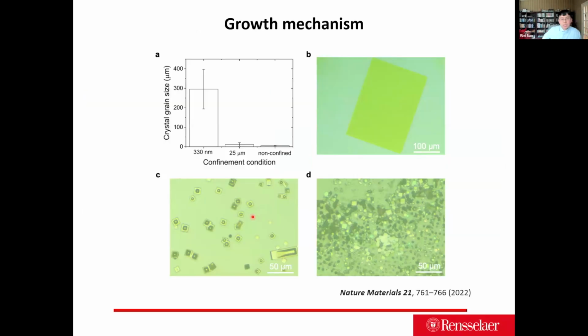So a little bit of growth mechanism on this. Essentially, if we have an unconfined structure, we are going to have a lot of the nucleation happen in the bulk solution. Once you have a lot of nucleation sites, you tend to grow a lot of small crystals. But if you confine this into a really small nano cavity, you have limited nucleation sites in the solution, and they never run into each other. They tend to grow bigger crystals, plus the template we have.